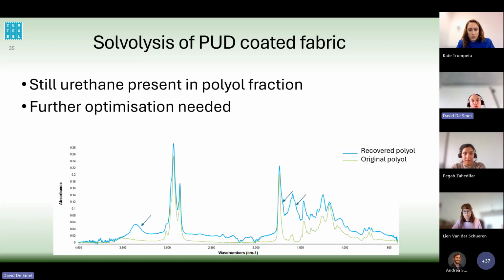Next to that, we're also looking into solvolysis of PUD coated fabric, which is, I would say, a little bit more difficult, because in the case of PUD coated fabrics, we also use cross-linkers to have a better durability, which is not used in the case of 2K, because 2K already on its own has a good durability. Why is PUD less durable? That's because we need to add some ionic groups into the backbone to make it dispersible in water. So during coating, we need to add additives to block these ionic groups to get a better durability. And of course, by adding these additives, you complicate the chemical recycling process, because there will also be other compounds next to your PU in the coating.